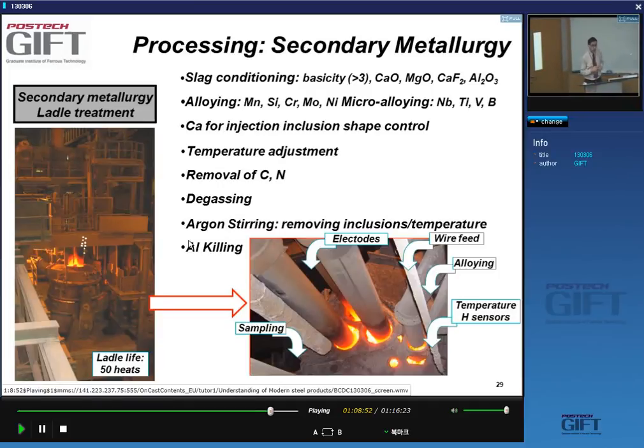After the BOF furnace, the steel contains a high level of oxygen, yes? So you get rid of it by means of aluminum. Aluminum forms an extremely stable oxide, Al2O3, yes? And that basically takes care of any residual oxygen there may be in the steel.